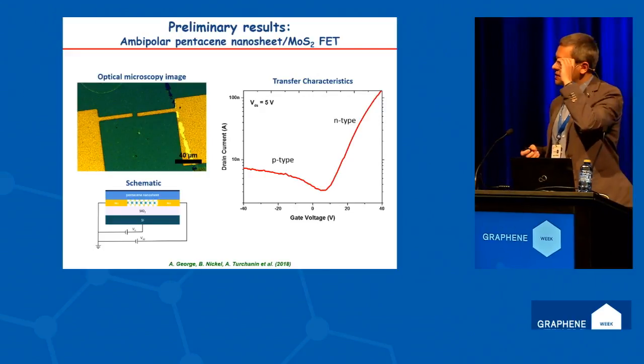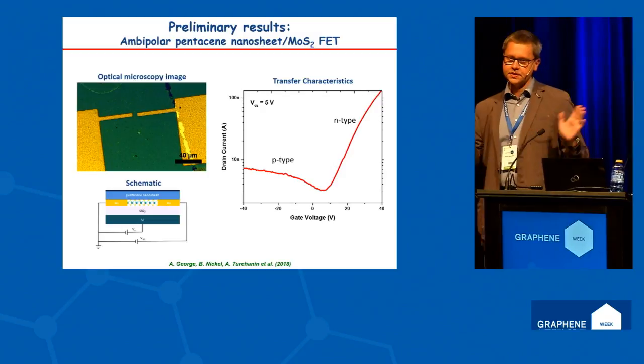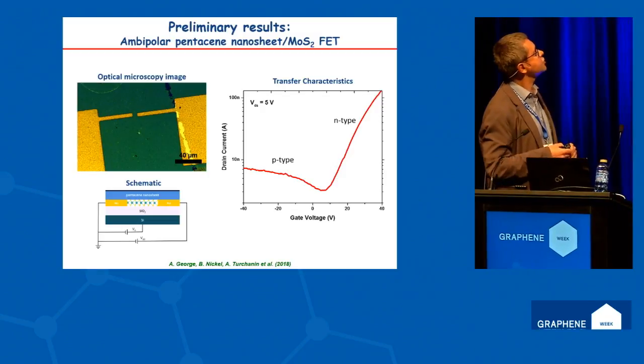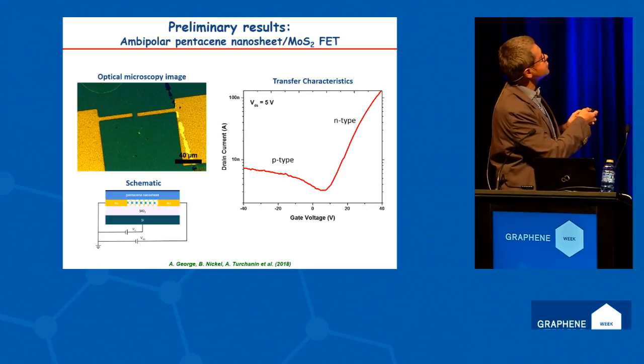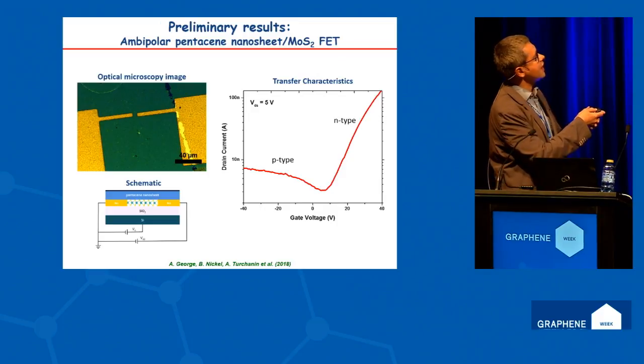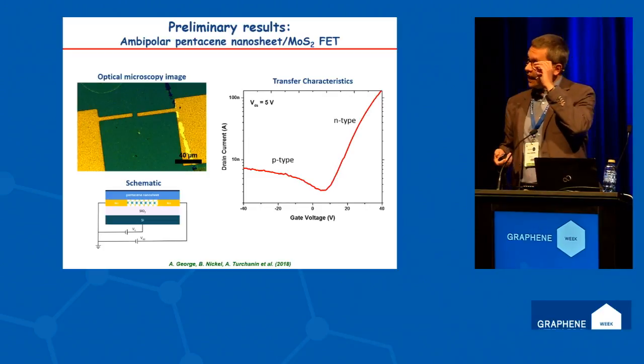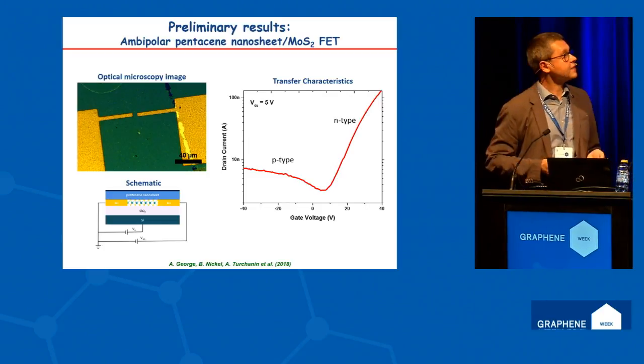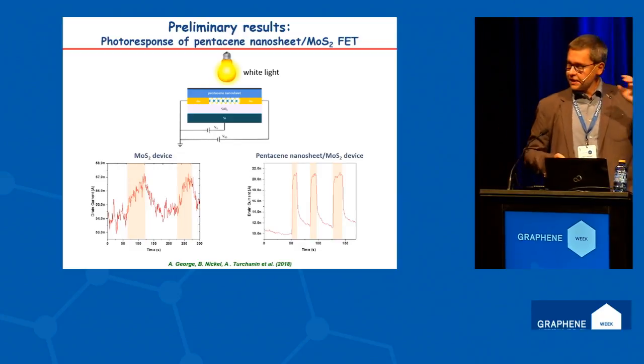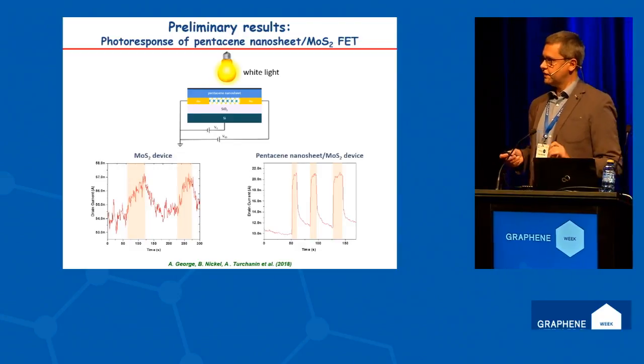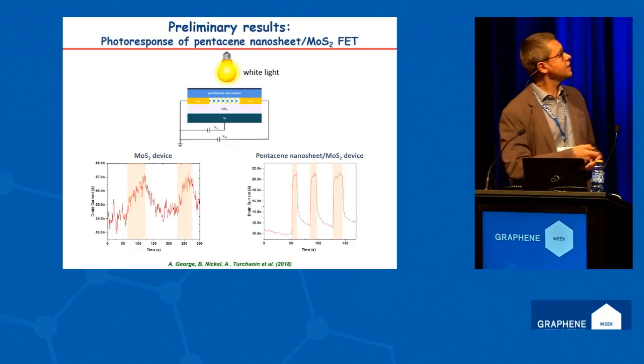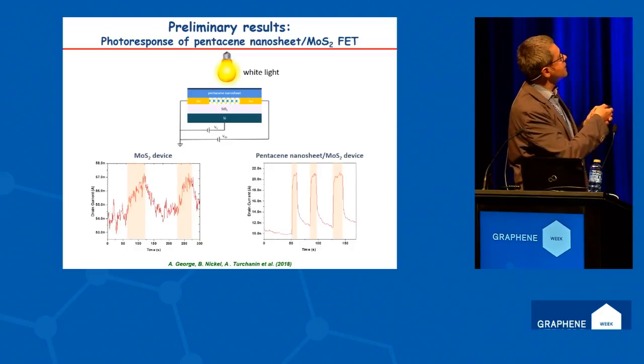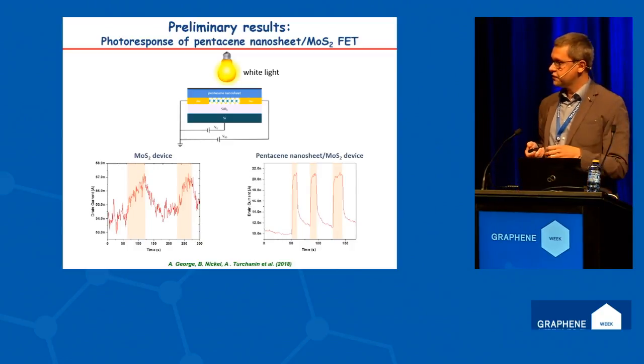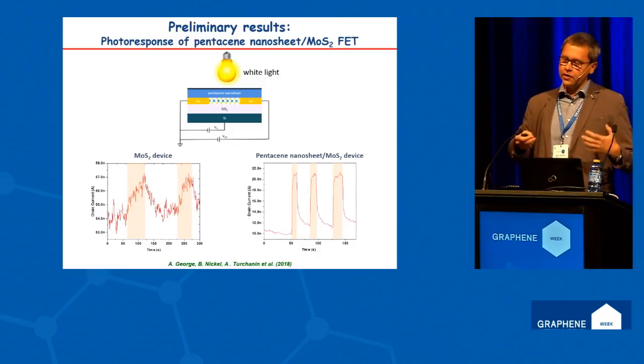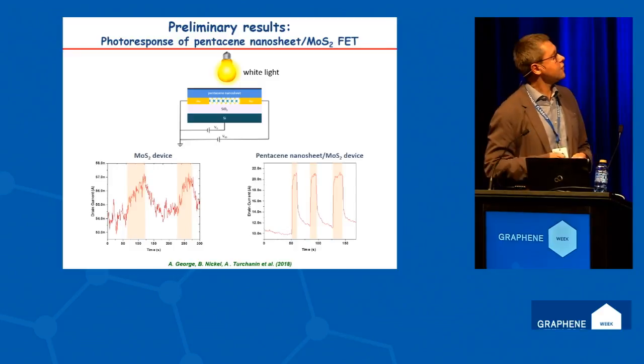And finally, this is the device characteristic. This is very fresh measurements, very preliminary data, but from such a device construction with 2 channels, a pentacene channel of P-type and a molybdenum disulfide channel of N-type, you produce a device showing a very clear ambipolar behavior, as we expect. It's very interesting that we recently started to study the photoresponse of these devices to white light, and we see strong enhancement of this heterostructure device in comparison to the bare molybdenum disulfide device, and now we are working on understanding the origin of this enhancement.